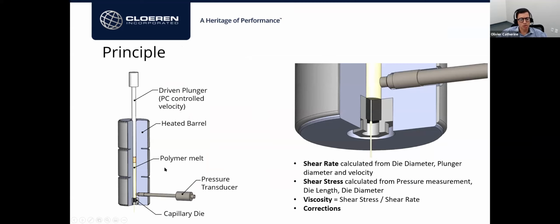So the principle is similar to that of the melt index, except that this now is instrumented. We load the polymer pellets in a heated barrel. The temperature of the barrel is controlled very precisely through a precise controlling system and measurement system, a thermocouple embedded deep in the metal of the barrel. Once the polymer is melted, we push it, but the main difference compared to the melt flow index is that we're not using a dead weight. We are using a controlled speed system, so we are able to control the speed very precisely. Through that, we control the flow rate, and the polymer is now flowing through a capillary die.